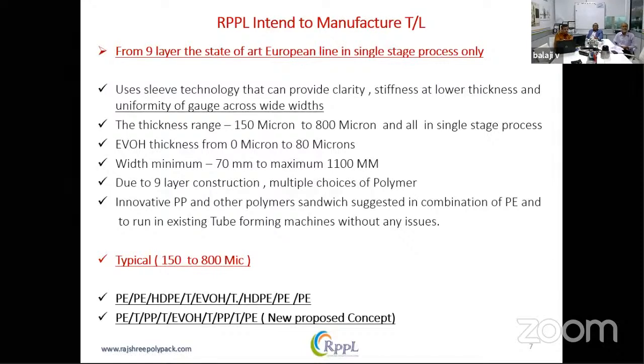We thank the audience. Our purpose is to introduce what we want to do. We are bringing one of the best lines, a 9-layer European line, which can produce tube laminate in a single stage process only. It uses the sleeve technology that can provide clarity, stiffness at lower thicknesses, absolute uniformity of gauge across the wide widths. The thickness can range from 150 microns to 800 microns, all in a single stage of production. EVOH thickness from 0 to 80 microns. Width is 70 mm to 1100 mm.